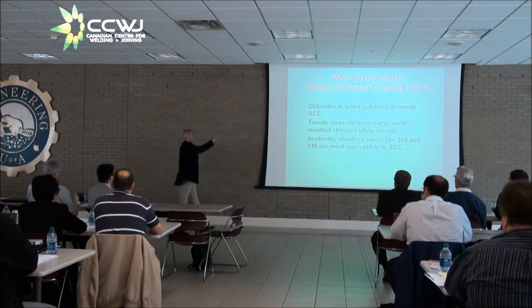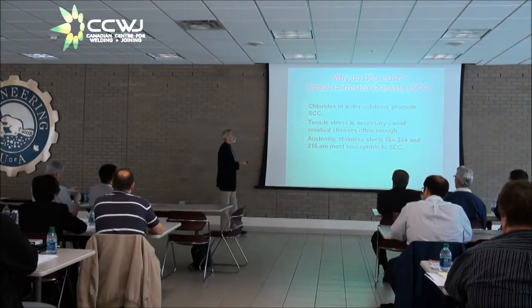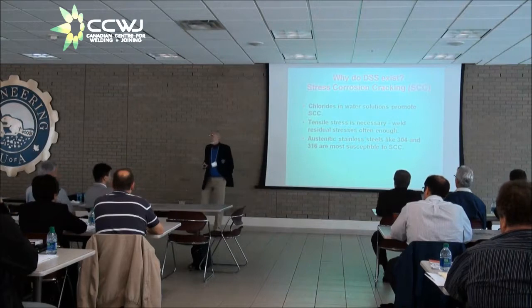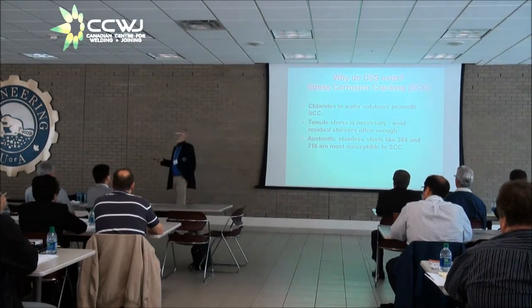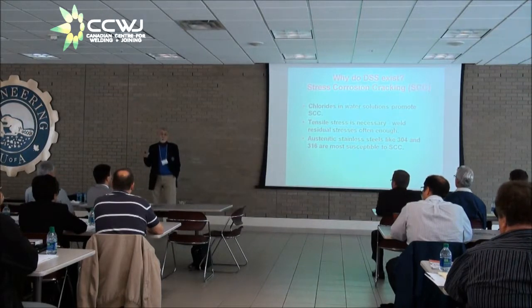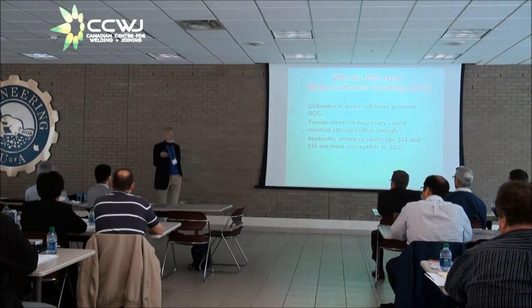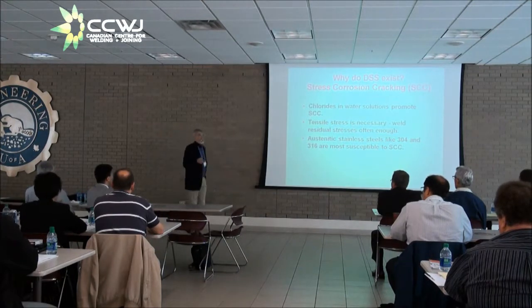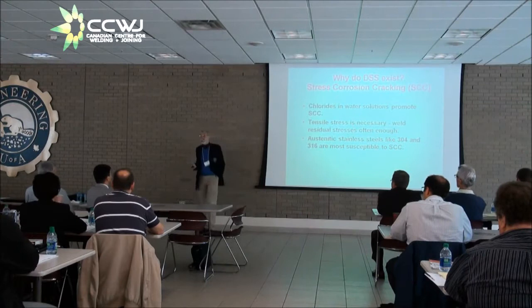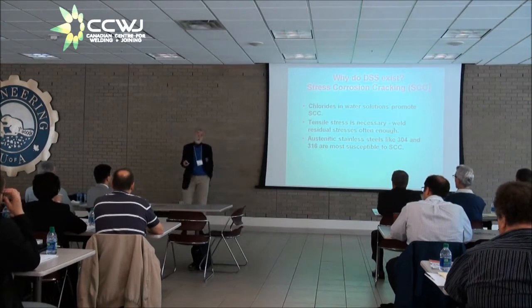So, anyway, in order to get chloride stress corrosion cracking, you need chlorides, you need tensile stress. Tensile stress is automatic with welds. So you can always anticipate yield point residual stresses around a weld. So you're always going to be susceptible to chloride stress corrosion cracking in alloys like 304, 316. That's why duplexes are interesting.